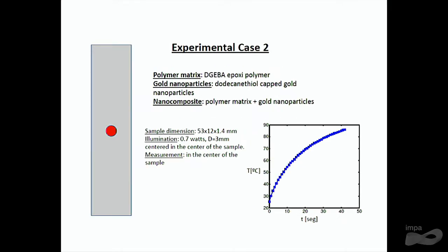This is a second experiment in which we have a different polymer. We have also different nanoparticles. The polymer in this case is an epoxy polymer. And the nanoparticles, I'm going to show you later, are much smaller than the ones of the first experimental example. The evolution of temperature is like the one shown here. This was measured in the laboratory. And it reaches about the same temperature, but in a much less time than before.